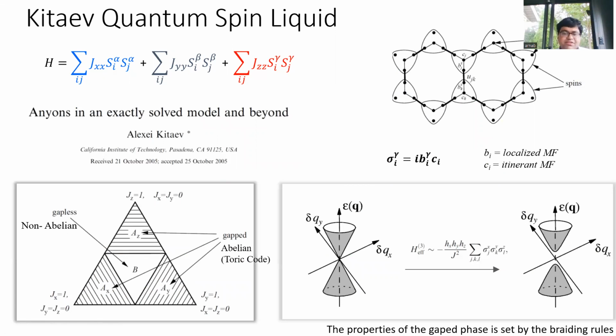And Kitaev pretty much solved this entire ground state. What he figured out is that you can get both gapped and gapless spin liquid states depending on the relative interactions between J_XX, J_YY, and J_ZZ. And when J_XX or J_YY win out, you get these phases where you get gapped abelian spin liquids, which comply with the toric code. But when you are in the gapless phase, what you get is these non-abelian excitations.